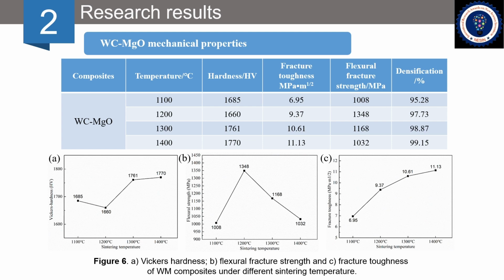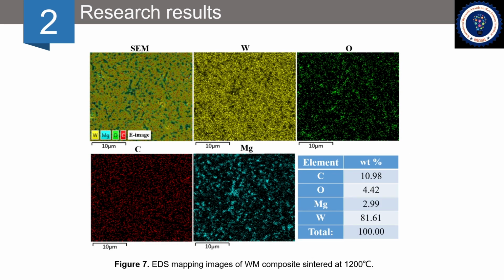Therefore, the strength of the tungsten carbide and tungsten carbide interface bonded without the binder phase was important to withstand the stress required for deformation. The specific reason for the sustained increase will be investigated by the microstructure of fracture. Next, WM composites sintered at 1,200 degrees were further characterized to investigate the mechanism of reinforcement and toughening. The SEM imaging of WM composite and EDS mapping were demonstrated in Figure 7.